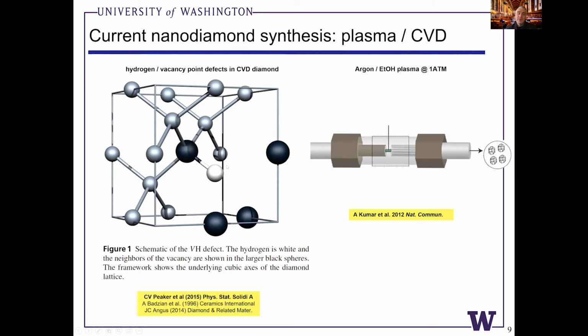Oftentimes you have a fair amount of hydrogen left over in the film, and the hydrogen atoms can passivate color centers in diamond like the NV center, which can reduce their brightness or the yield you get following implantation. Hydrogen is kind of a challenging mystery element that has to be considered when trying to make point defects in a CVD approach.